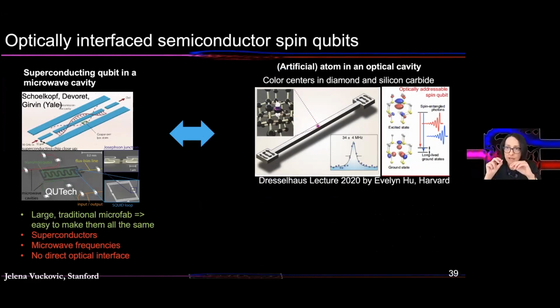Really, our quantum bit is an individual impurity defect inside of the material. For example, here you see a tin impurity, an extra tin atom embedded inside of diamond. But likewise, you can have silicon in diamond, or you can have missing silicon atoms in silicon carbide. And this is like a naturally trapped atom or ion inside of this solid. It's the same as atomic physics experiments, but you don't need a trap to trap the atom or ion. It's already trapped by the lattice. Of course, that leads to interaction with the environment, so you have to make sure that you minimize defects and minimize that interaction, because it's not really a vacuum, but physically it is the same platform.